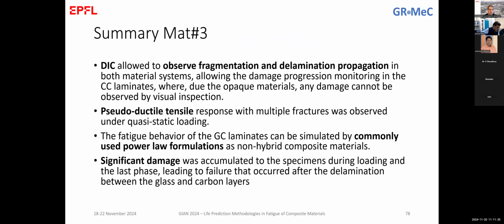So to summarize again the third material, we saw that we can use DIC to observe the fragmentation between the layers, the delamination propagation in both materials. We've seen also that there is a nice effect of the hybridization. With this, we managed to have a pseudoductile tensile response, both in quasi-static and fatigue loading.